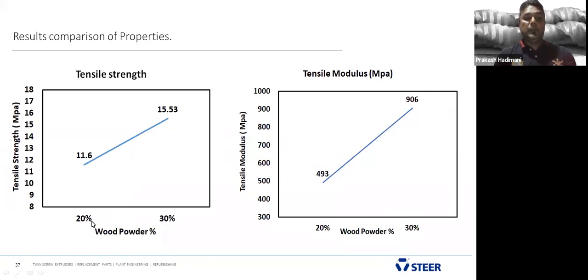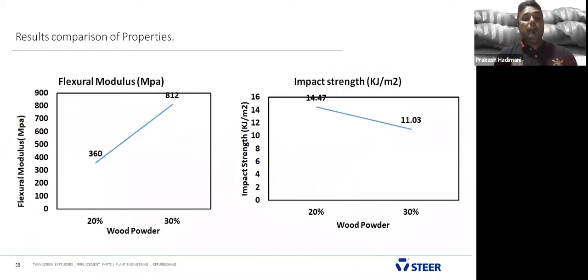20% addition of WPC wood powder with PBAT is giving a tensile strength of 11.6. With the addition of WPC, there is an increase in the tensile strength, and similarly the tensile modulus increases, so the addition of wood composite increases the mechanical property. The trend also holds for flexural modulus. Addition of filler, wood powder, is increasing the flexural modulus.